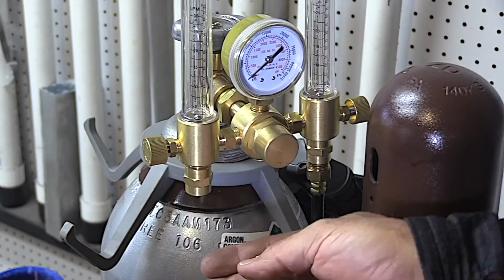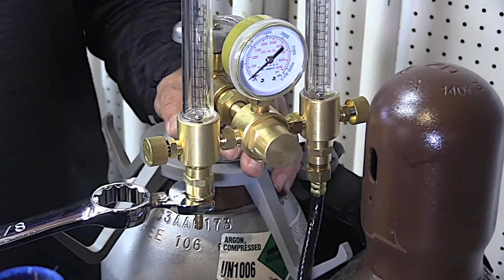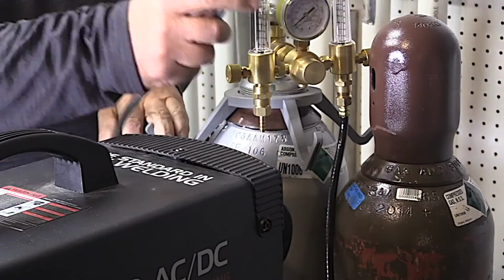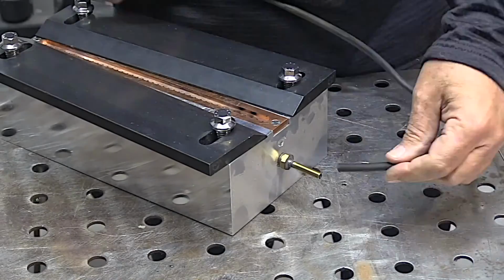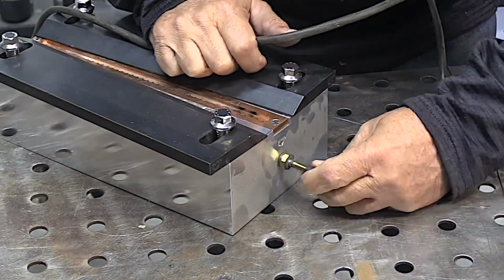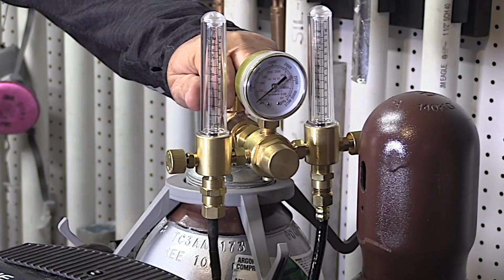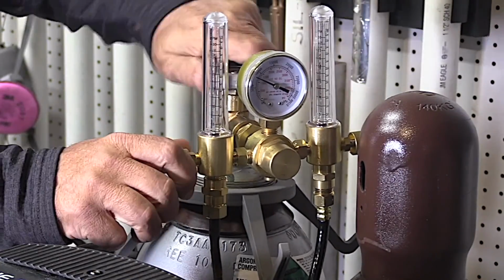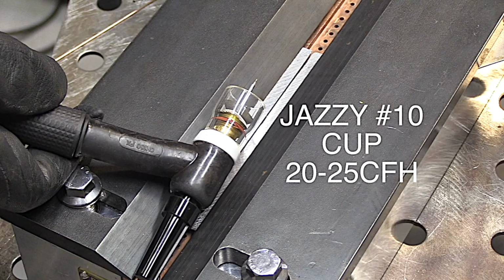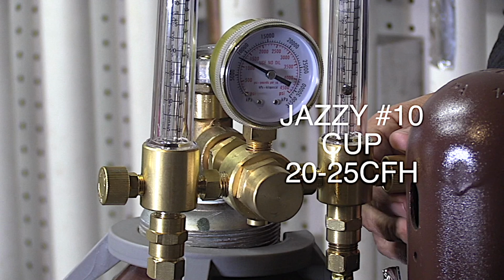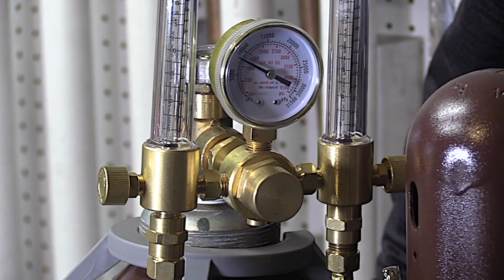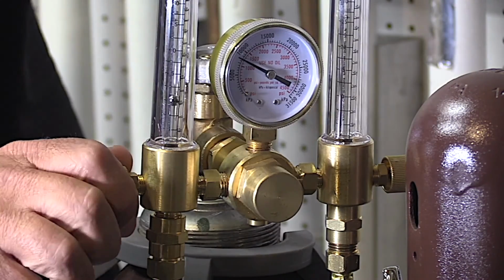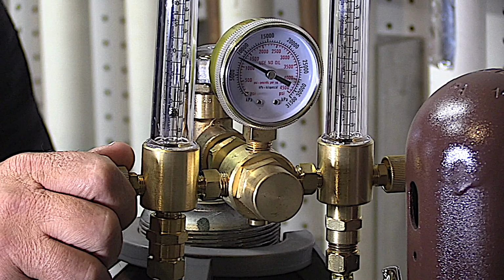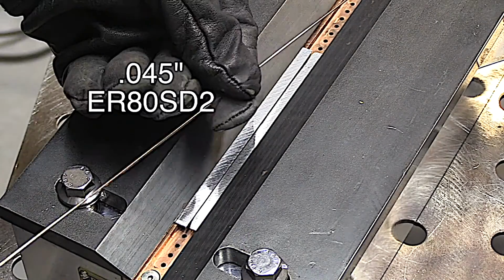To get purge gas to the back side of the joint, I'm using a dual flow meter. You could also use two separate cylinders with single flow meters, but the dual flow meter is an easy way to do it. I'm just using regular old automotive vacuum line for the purge hose. That's fine for cold rolled steel. You might need something better for titanium and exotic alloys. If you ever have to take a test like this, you want to be careful not to use too much purge flow on the fixture. That'll blow your torch gas away.